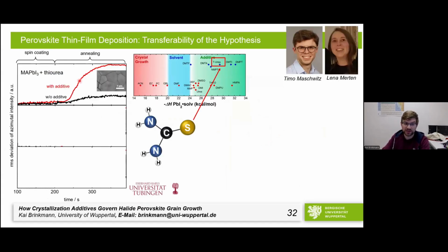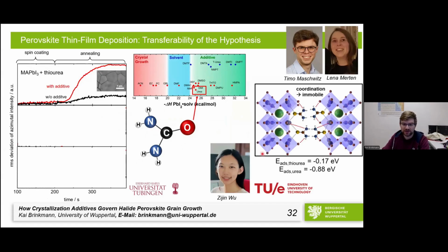of them. So first of all, what I showed you is actually methyl ammonium lead iodide. I forgot this in the beginning. So this is methyl ammonium lead iodide with thiourea. This is like the GIWAXS data. So it looks like I already told you. If we go from thiourea to urea, we actually have almost the same kind of behavior. So it's also an ionic shuttle. But DFT tells us that the adsorption energy of urea is stronger. So urea has a lower chance of shuttling the ions. And having a look at the grains at the end and also having a look at the GIWAXS, we see the same effect. It also comes with the annealing, but it's a bit slower. It's a bit less large in terms of grains.